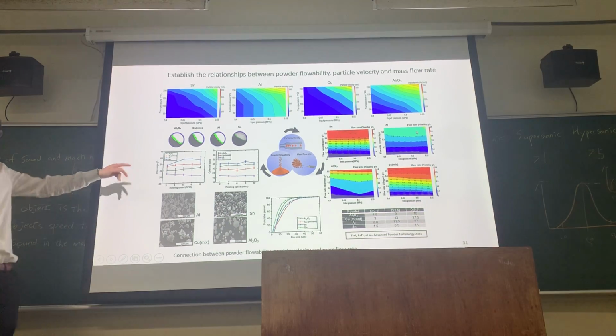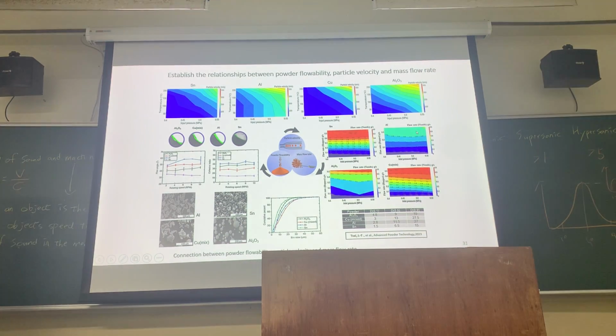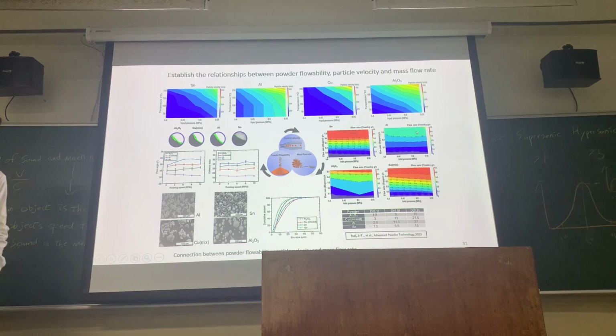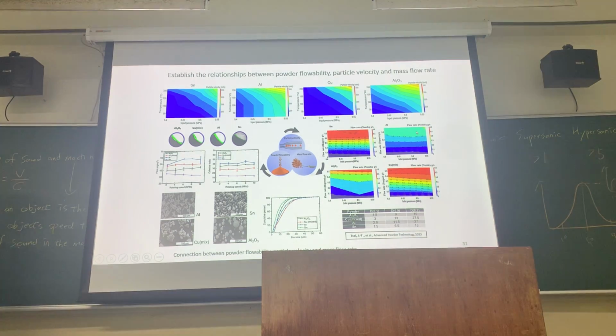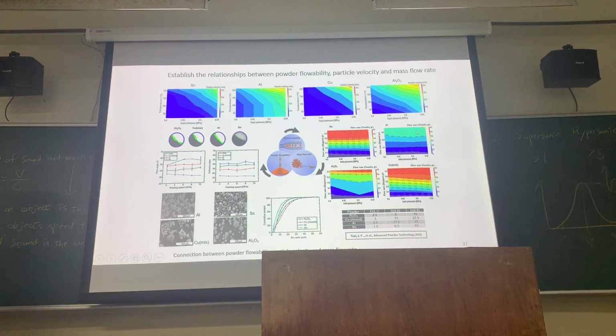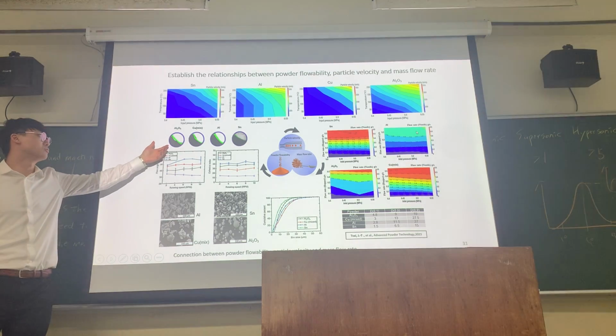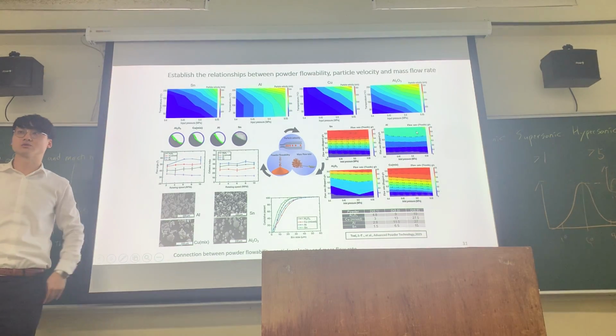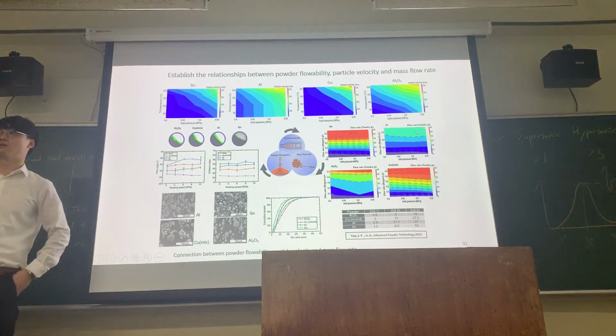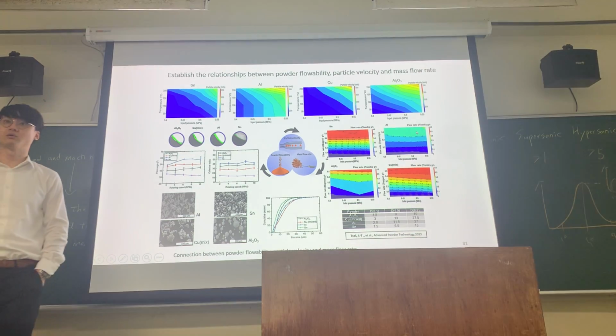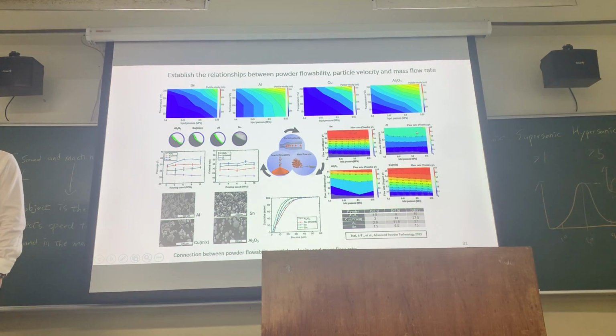Over here, there's the powder flowability. Sometimes when you read a lot of articles in particle technologies, there's the question of how do you quantify powder? It's basically by putting powder inside a drum, allowing it to rotate, and measuring the angle. So this is fairly easy. This is also according to a standard, an ASTM standard.